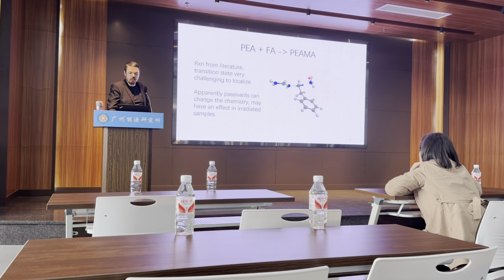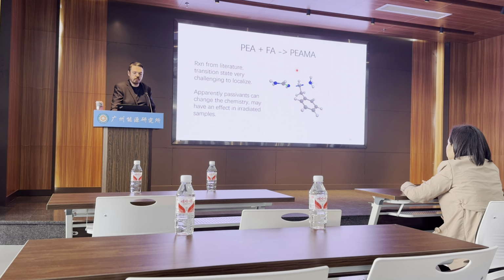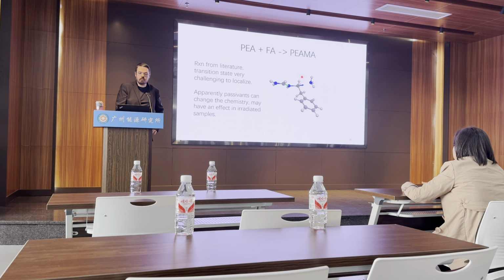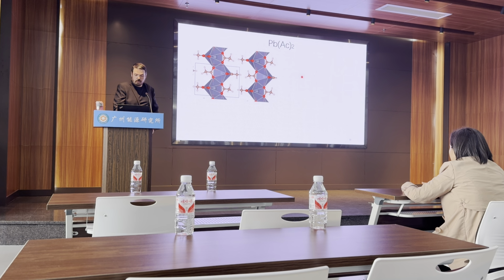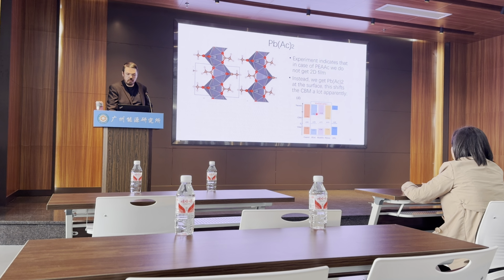And just to say, this kind of calculation is tough to do. Getting the transition state this well takes a lot of work. But from what I heard from Pavel, it seems like the transition state energy is comparable to experiments. So that's exciting. Also still unpublished. So the final result is that experiment indicates this acetate-based PEA does not yield a 2D film, but instead yields this PEA acetate. And this apparently shifts the CBM a lot, so here it is. In these cases, you see the conduction band is kind of high.